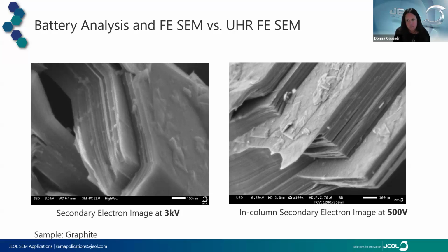This is a comparison of a conventional field emission microscope image on the left versus ultra high resolution, or kind of our flagship field emission microscope, on the right. With these ultra high resolution instruments, we're capable of ultra low voltages. We are using in-column detectors, which give us great resolving power. So you can see the difference in how sharp the image is, and we can really see the layering in that graphite particle, really at the nanometer scale. So lower voltages also means more surface structure can be observed. And that is really readily apparent if we look at the surface up here.